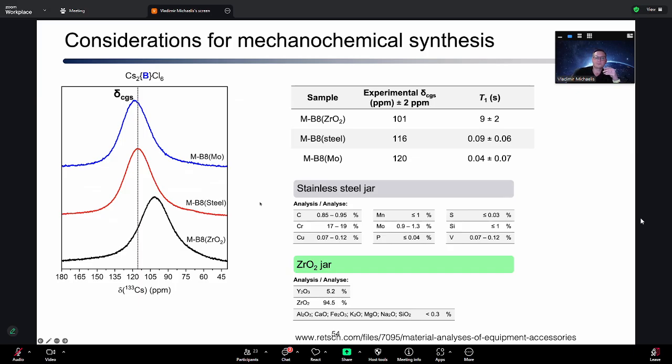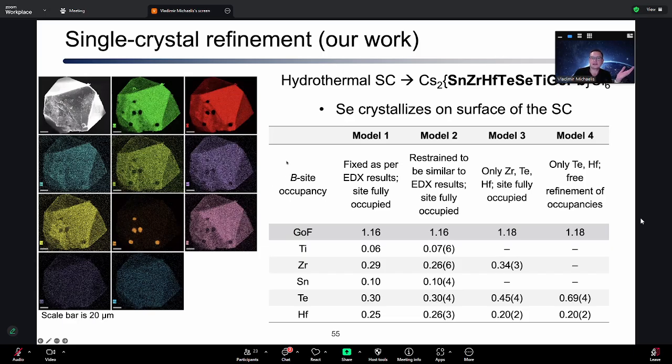Okay, let's go back to that single crystal. So how was that initial study out of Nature able to get homogeneous systems? Well, interestingly enough, here's basically an 8-component system. And what you can see here is you have selenium that basically phase separates, but the rest of the elements are fairly well homogeneously dispersed throughout the whole material.